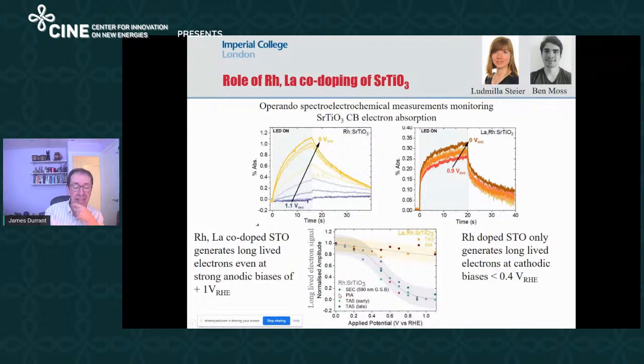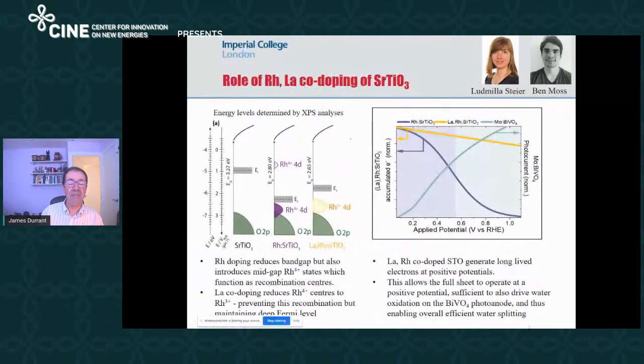You can see the plot of that here. So this is the long-lived electron signal versus voltage. And you can see that when you've got the lanthanum co-doping, you can generate long-lived electrons even when you apply a positive potential to the material. And that's quite surprising because you'd imagine to drive a reduction process, you want to apply a negative potential. But this is able to work as a reduction system at plus 1 volt. And that's why the system works.